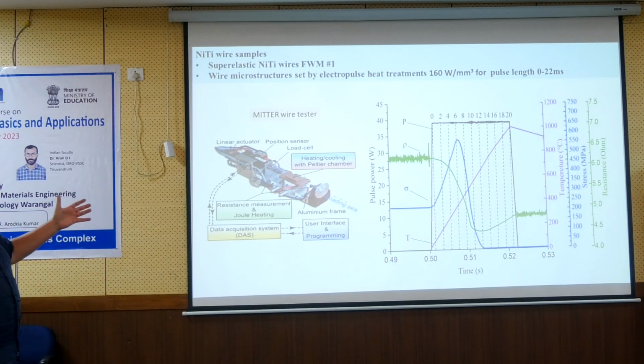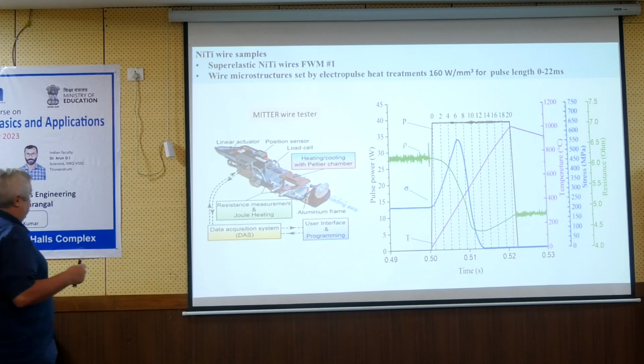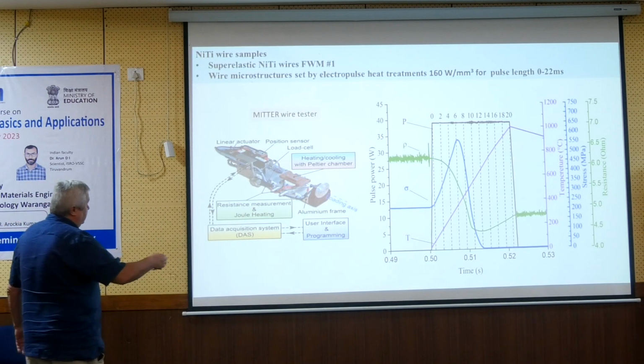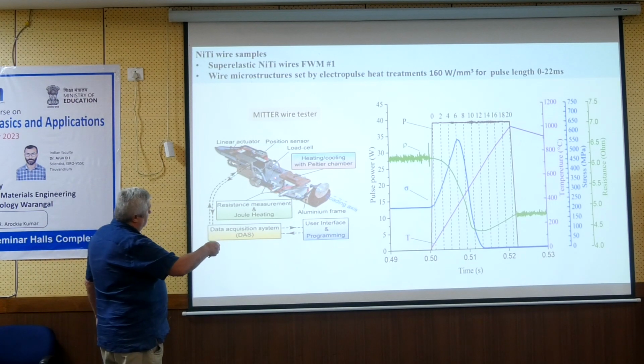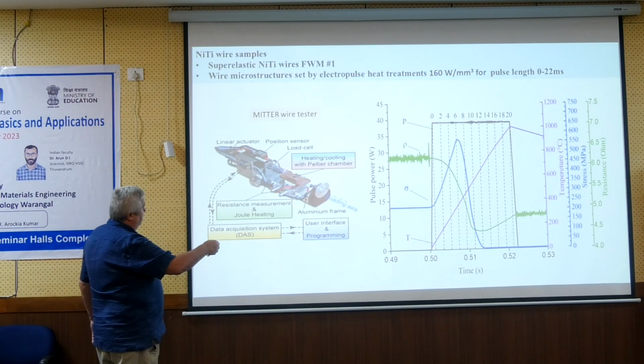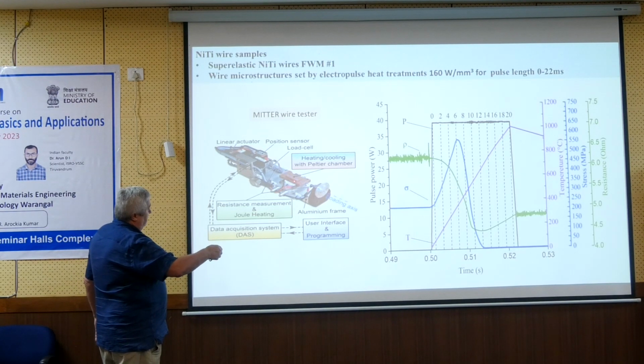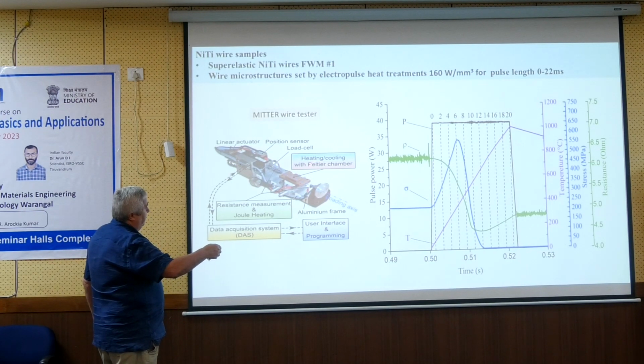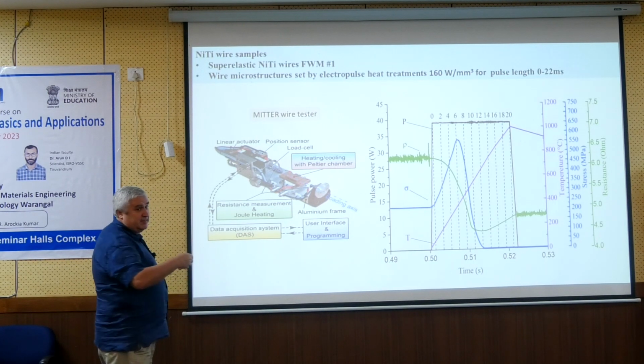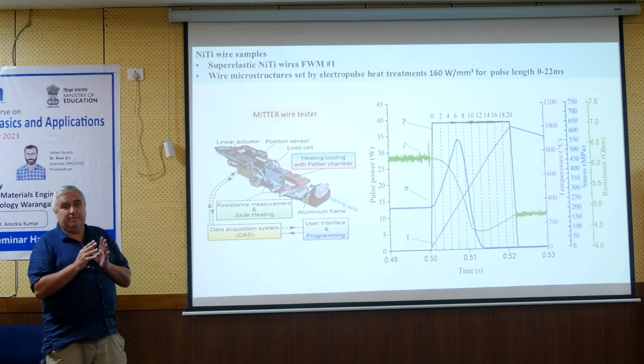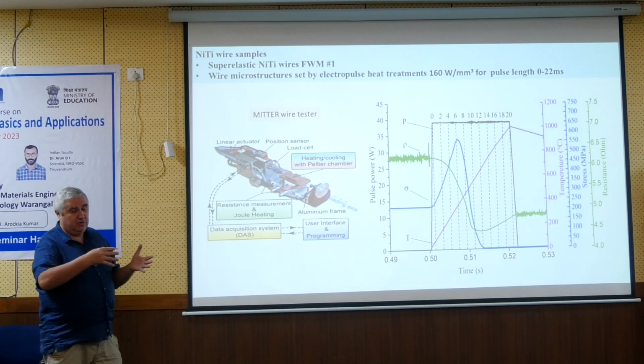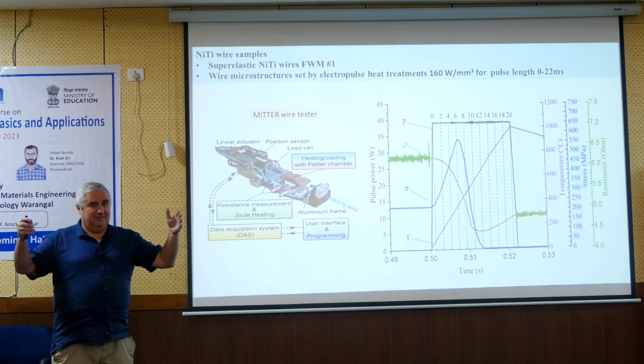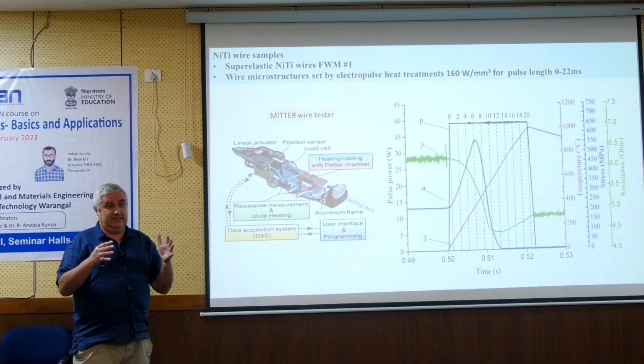So we started to develop some small tensile testers with a LabVIEW control system, which can perform loading and heating. This is a copper environmental furnace, which is operated by Peltier elements inside. It's covered, so you can perfectly control the temperature inside, and because the filament is thin, it's pretty precise. It's completely closed, so there is no wind, because if you have a thin filament, any kind of wind blowing will completely change your stress-strain characteristics.